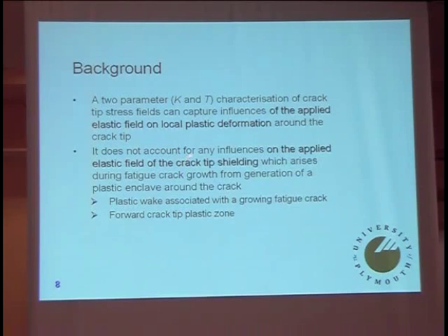What we're not able to do yet is really account for any influences on the applied elastic field of this plastic zone around the crack tip. That remains the complex bit. And if you say, well, let's just do K max minus K minimum, in other words, delta K effective, you are not capturing those effects properly. And that's well known because lots of work has shown that the range of effective delta K is different to K max minus K minimum.